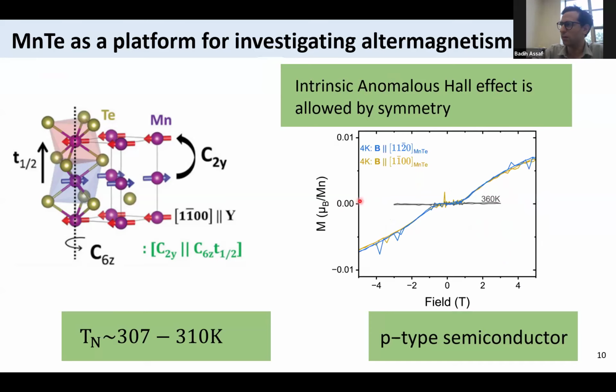And you can see that below what we call the spin flop field, essentially at zero magnetic field, the magnetic moment is vanishingly small. We cannot even detect it by SQUID magnetometry. We can put an upper bound on it that's on the order of 10 to the minus 3 Bohr magnetons per manganese, but it's really an upper bound. It's not a measurement.